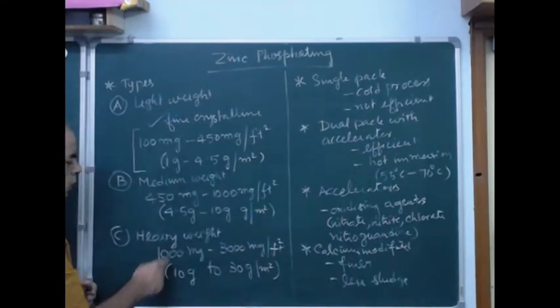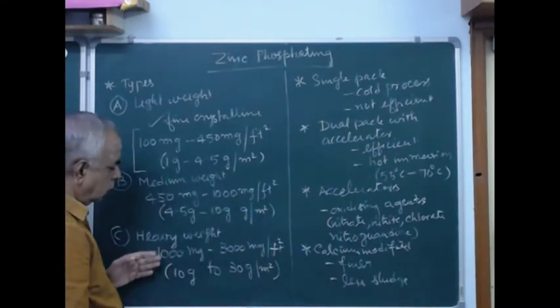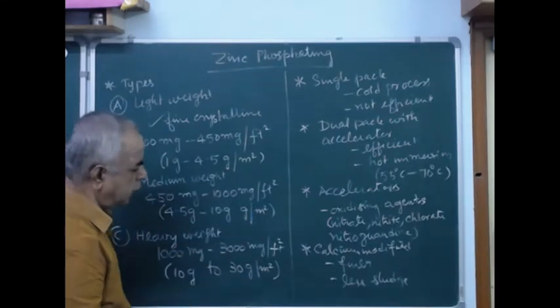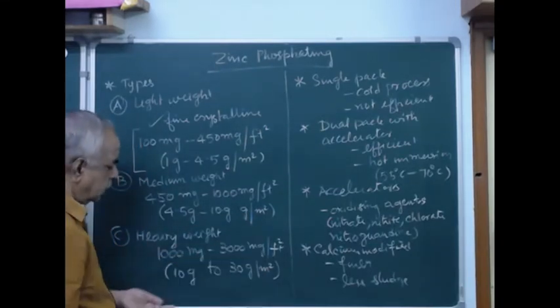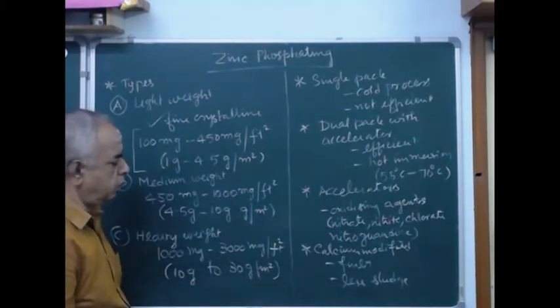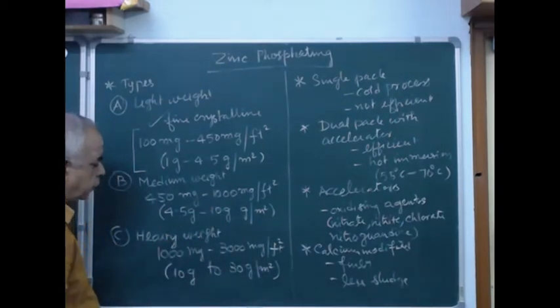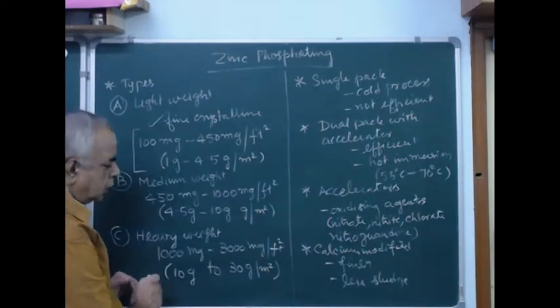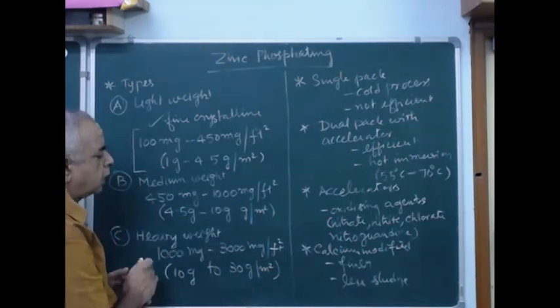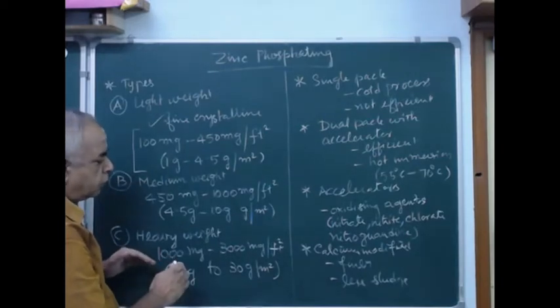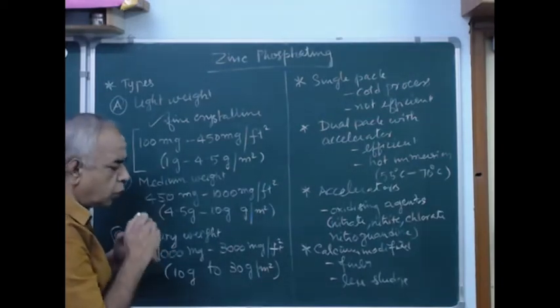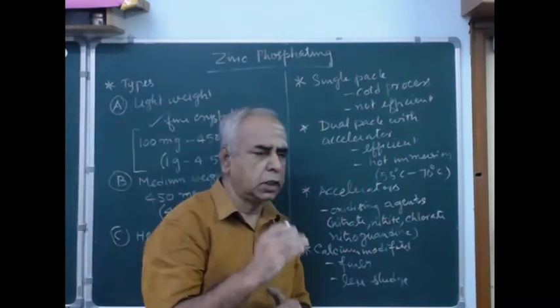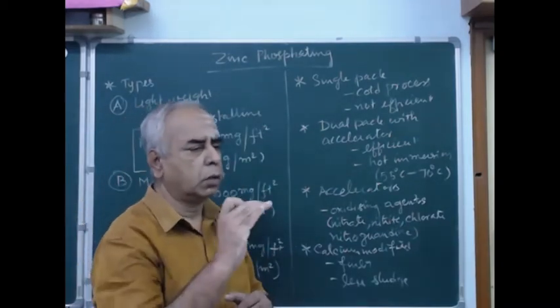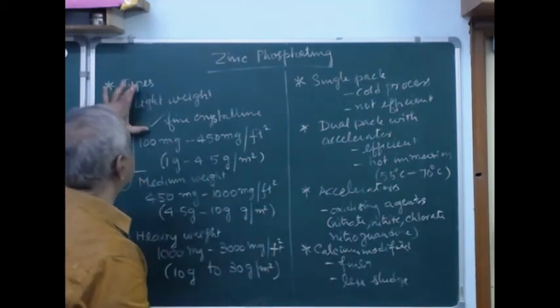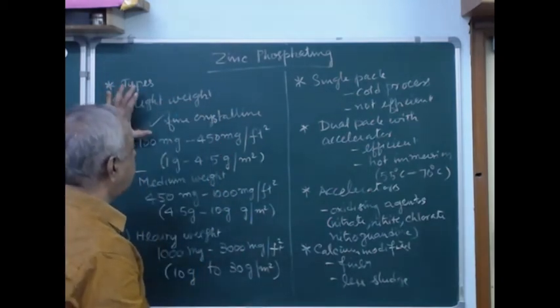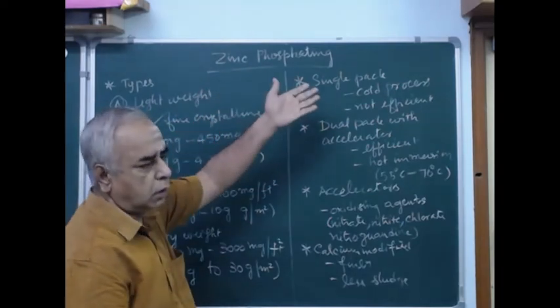And the third variety is heavy weight. Here it is 1000 milligram to 3000 milligram per square feet, that is 10 gram to 30 gram per square meter. Okay. So here it will be slightly porous and it may not have an aesthetic appearance, and it will have a matte finish also. So if you want to have a super glossy finish with a single coat of finish or double coat of finish, then I would suggest you go for lightweight, where you cannot get the highest corrosion resistance.